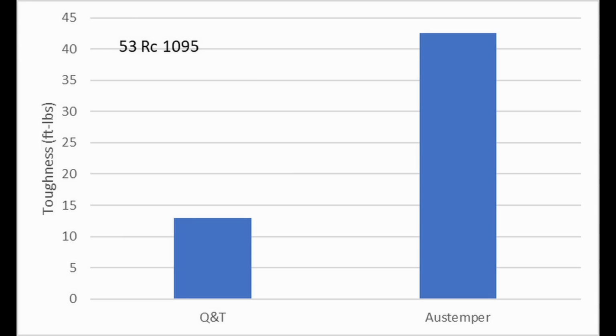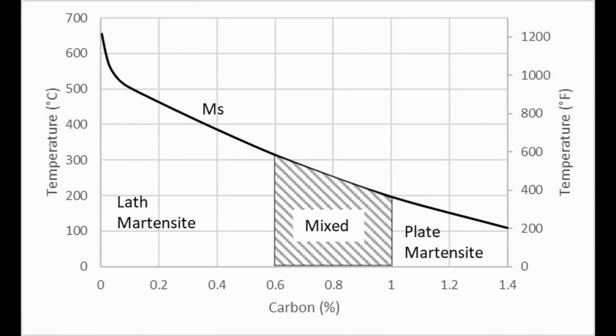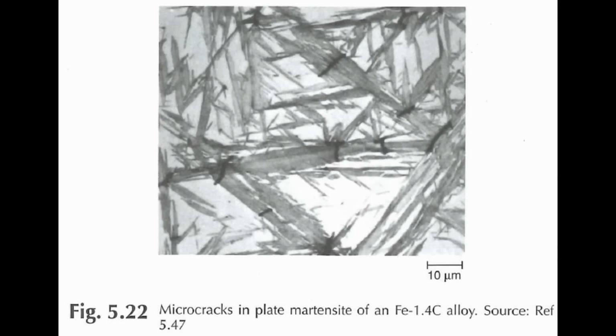Well, one of the reasons is something called plate martensite. As martensite gets higher in hardness, it transitions from the normal structure called lath martensite to a more brittle structure called plate martensite. It transitions to plate martensite at about 1% carbon, but above 0.6% carbon, it starts to get more and more plate martensite mixed in with the lath martensite. So plate martensite is more brittle, and sometimes when they look at the microstructure of plate martensite, they'll even see little micro cracks inside the plate martensite.